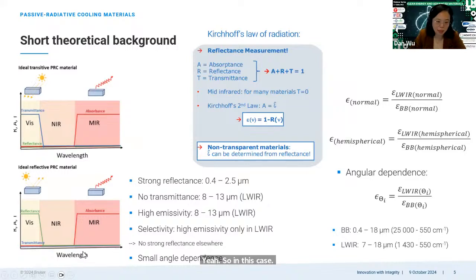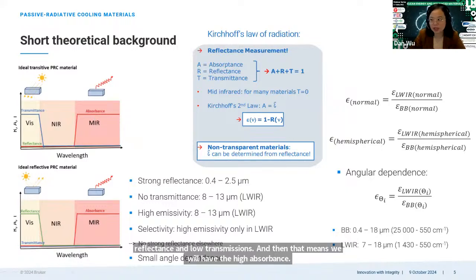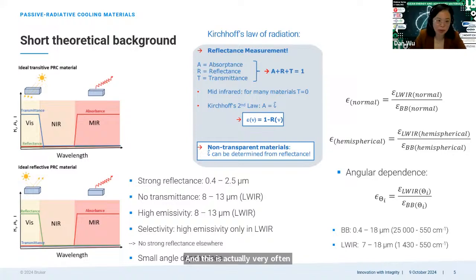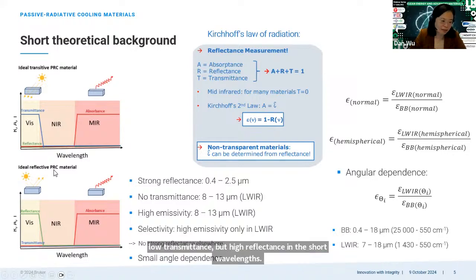So in this case, we have the clear design purpose of a passive radiative cooling material: in the thermal radiative wavelength, which is the mid-infrared range, we should have low reflectance and low transmission, which means we will have high absorbance. This is very often the case for organic materials, especially polymers. Then in the short wavelength range, we can either have low absorbance plus low reflectance, which means high transmittance, and this is called the ideal transmissive passive radiative cooling material. Or, on the other hand, we should have low absorbance and low transmittance but high reflectance in the short wavelength, and this is the ideal reflective passive radiative cooling material.